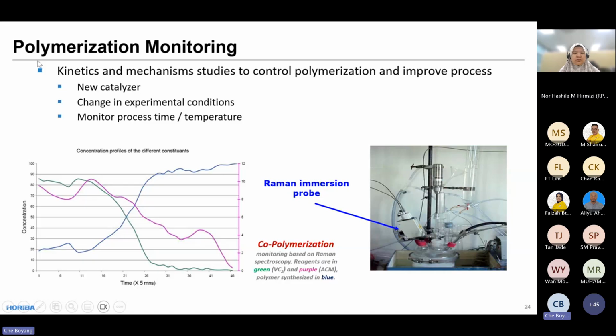We can also monitor the polymerization process using the Raman. So in this case, we put a Raman probe inside the reaction container. And once the reaction starts, we can monitor the Raman signal intensity, and we can see the signal from the raw material start to drop, and the signal of the final product start to increase at a certain time. So this gives us the polymerization reaction information, and we are able to optimize this reaction by changing either the concentration of the sample or by adding the catalyst. You will see a different reaction rate based on this curve.